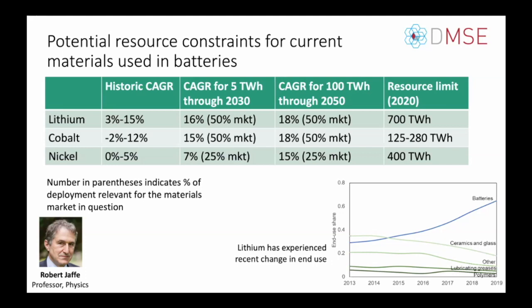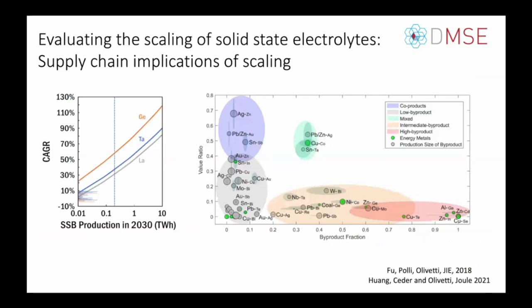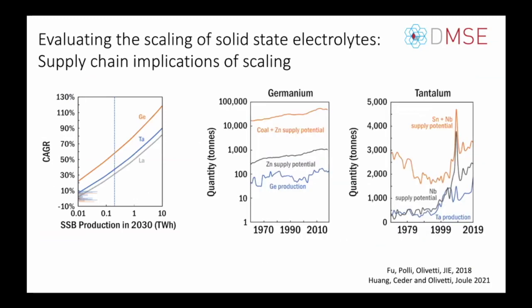I'm headed towards the end of my time here, and I just wanted to bring this back a little to my interfacial point around solid state electrolytes. We did a similar analysis looking at a couple of strategies pursued for interfacial resistance mitigation in solid state electrolytes, looking particularly at germanium, tantalum, and lanthanum, going through the screening analysis I just gave you some metrics around. These were the elements that popped out for further consideration related to solid state electrolytes more broadly.